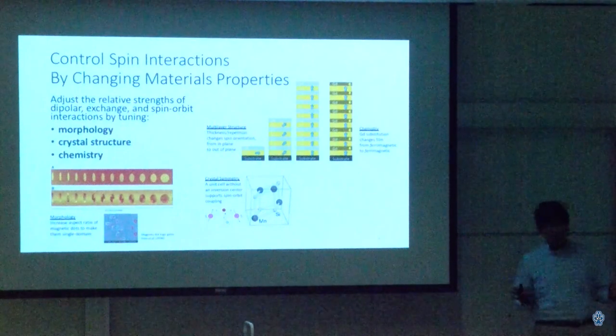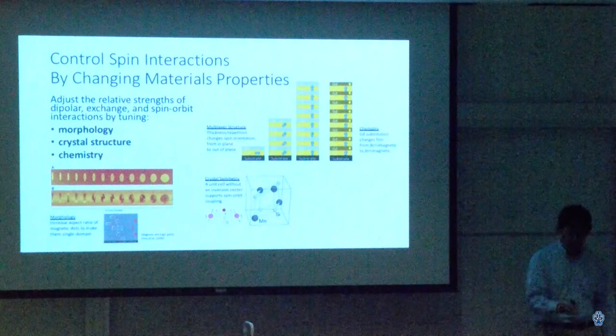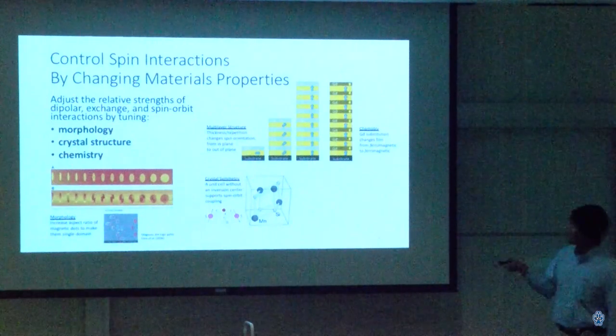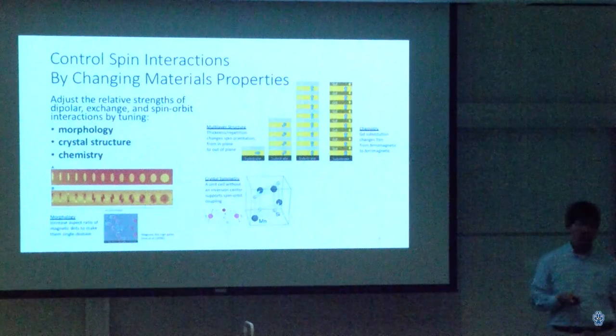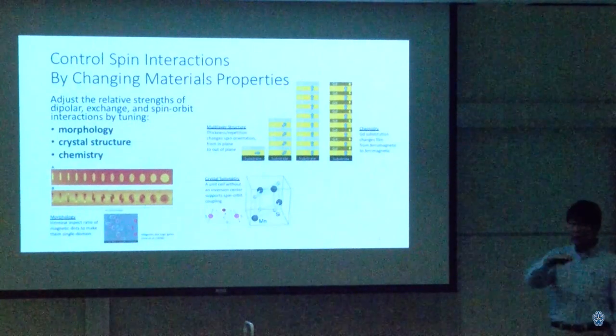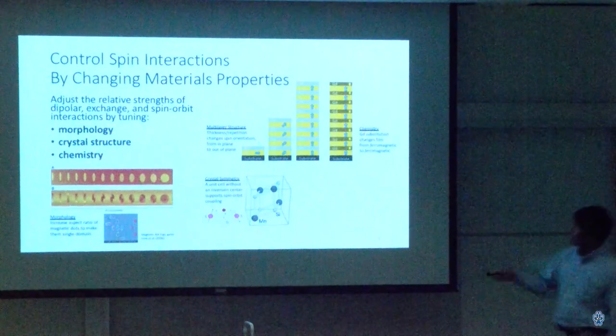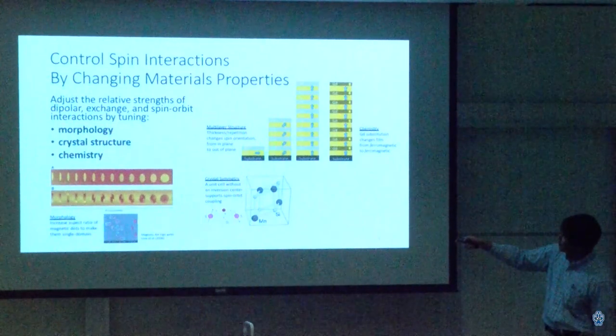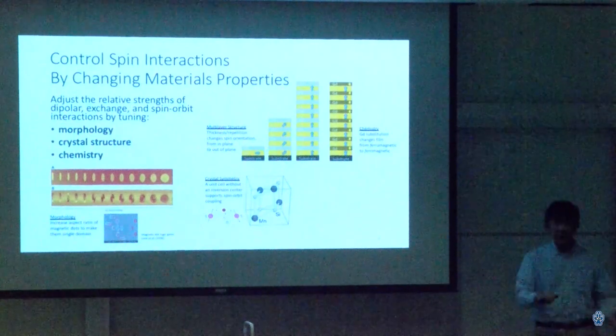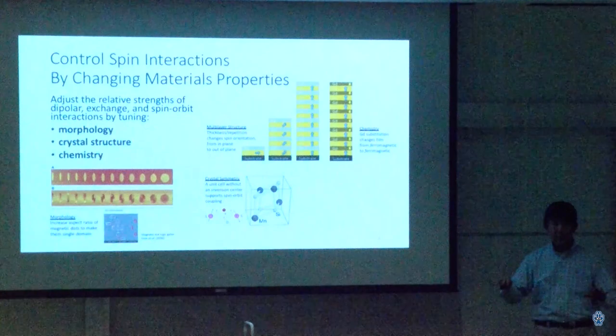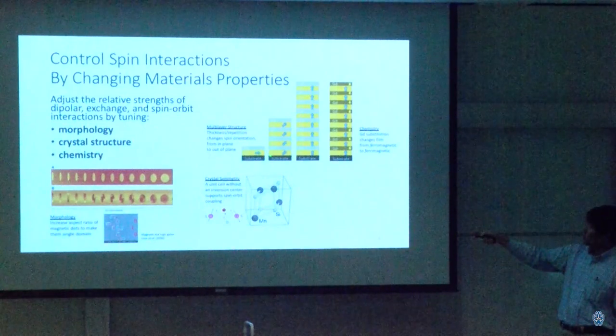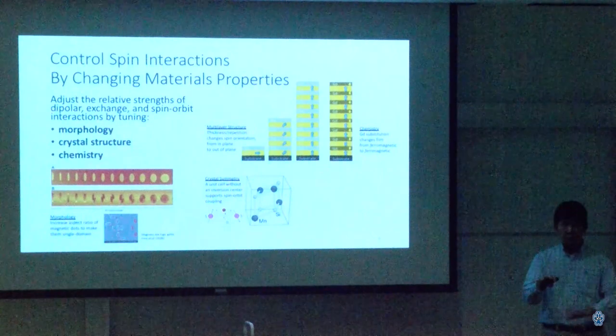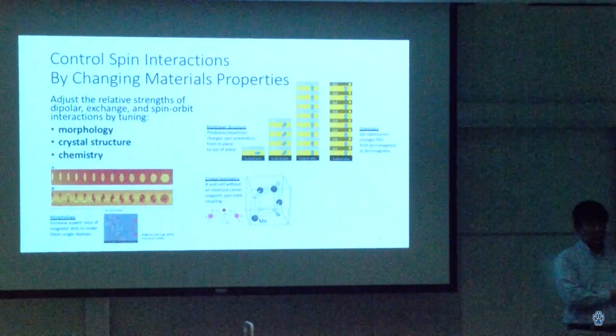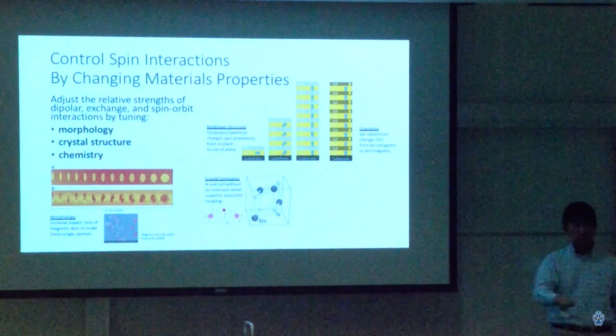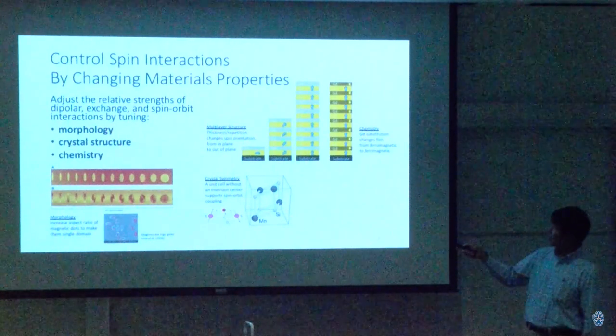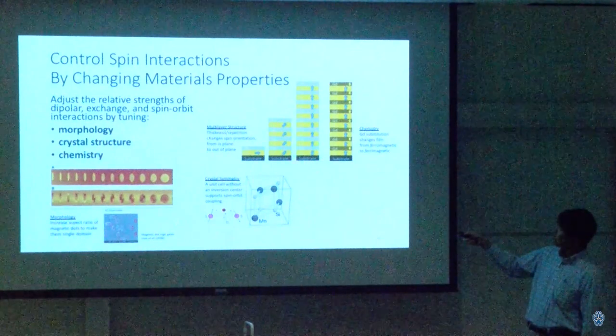If you're not interested in natural crystals, you can produce artificial crystals, or just something that has a regular modulation. In this case, the example I'm using here is a so-called multilayer, or a thin film that is chemically modulated from the bottom up. The labels here are hard to read, but the yellow is cobalt and the gray is palladium. And the idea is you can lay layers down onto a flat substrate and have a magnetic moment spontaneously appear. With one set of cobalt and palladium layers, the magnetization, or the magnetic moment of the film, might point inside the plane of the film. But the more repeats that you have going up causes the magnetic moment to eventually cant and point straight out.